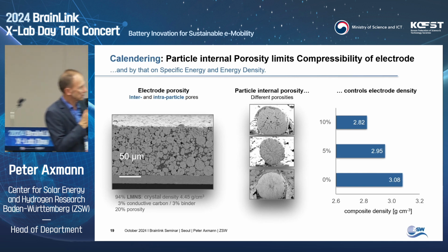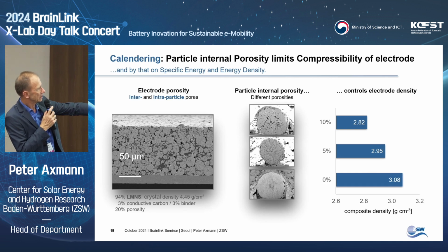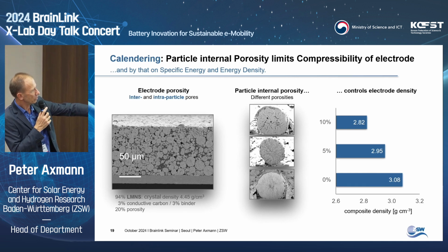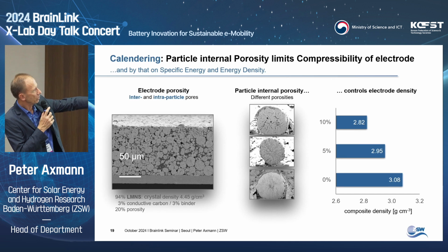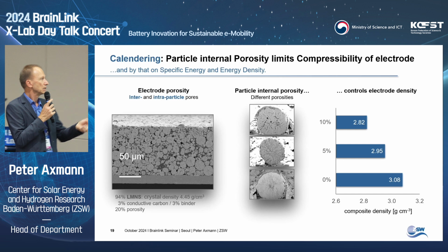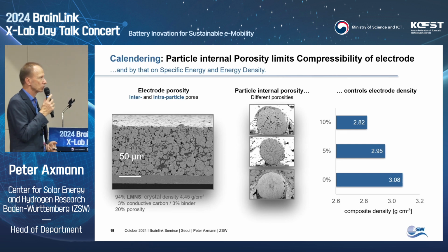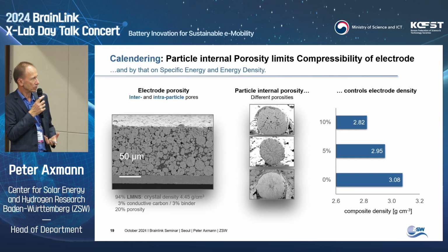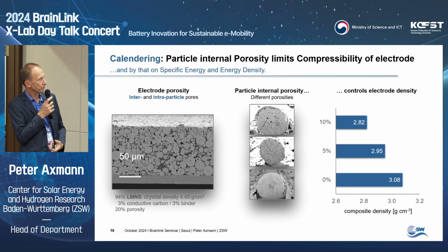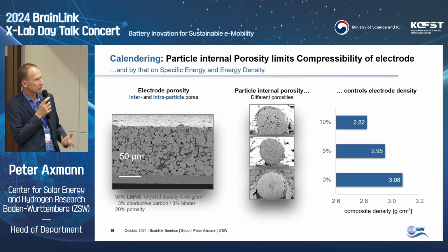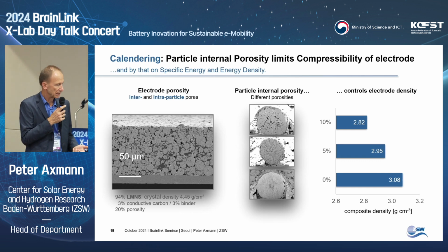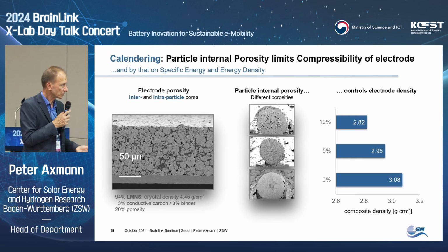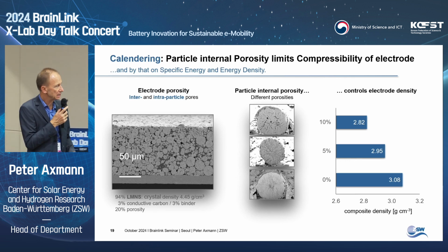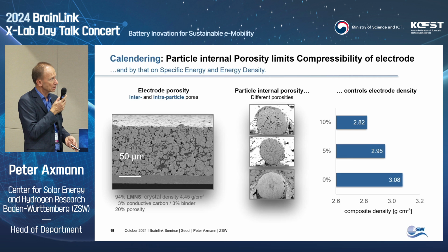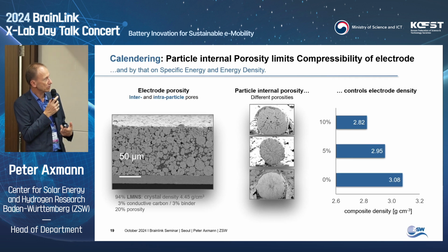And if we calculate just here for a dense material the theoretical capacity for a 20% porous electrode and go up with 5% internal porosity, 10%, we see that the density of the electrode goes down, which means we get less of the material in a cell of a given volume. And in addition, you have more porosity to fill with the expensive electrolyte. So you have lower energy density at higher cost. So this plays a role as well, which is very important.